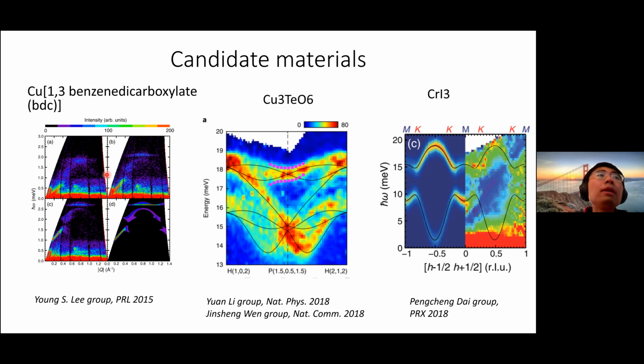For example, here in copper 1,3 BDC, this is actually known as a metal organic framework material. In this material, the copper spin 1/2 moments live on a two-dimensional Kagome lattice. In this system, the theory prediction is that in a two-dimensional Kagome lattice magnet, the Dzyaloshinskii-Moriya interaction between nearest neighbor spins can open up a gap in the spin wave spectrum at certain momenta, k and k prime points, zone corner.